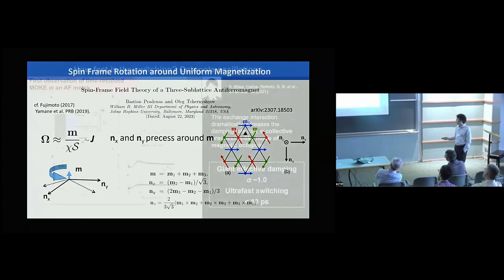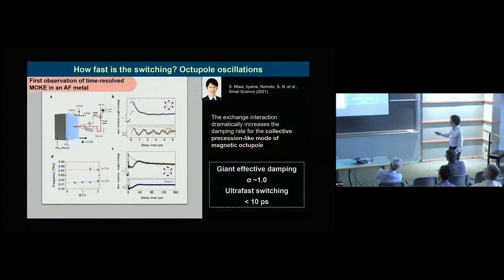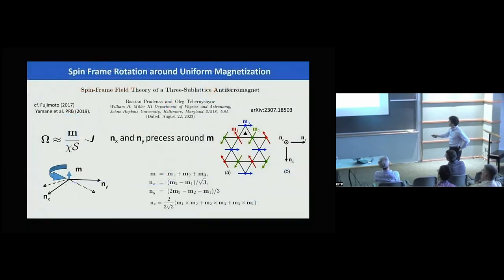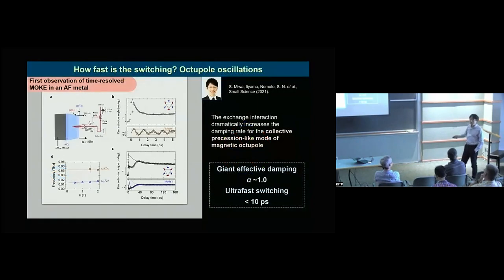So that is the method for the spin orbital. Before going to that, we wanted to tell we have evidence of such a spin precession at the time scale of these terahertz. Because another important point is that omega is actually proportional to 1 over chi, or this exchange coupling. So the beauty of antiferromagnetism is that in comparison to ferromagnetism, you can go to faster dynamics, to the terahertz scale. In fact, this is time-resolved magneto-optical Kerr effect.